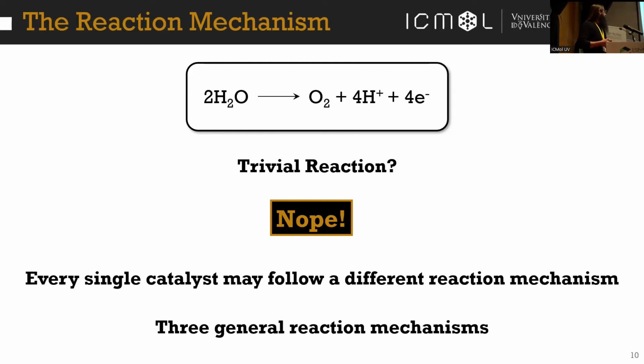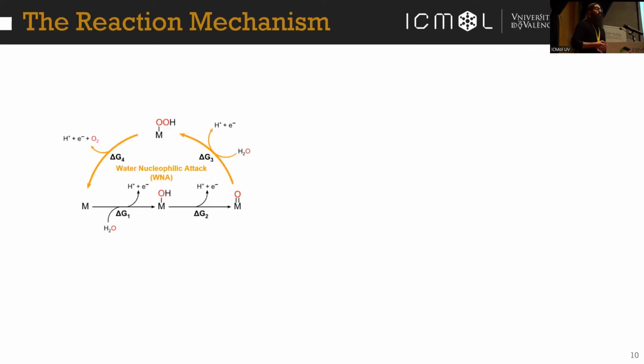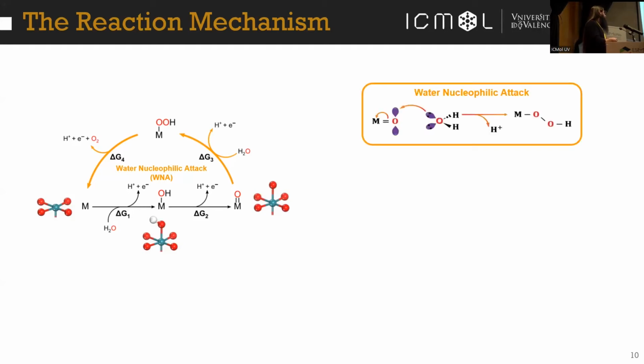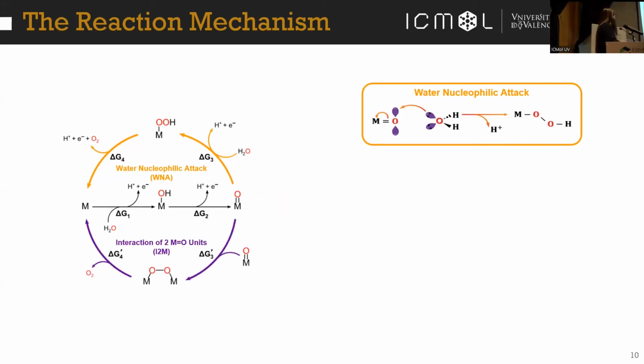So the first reaction mechanism is known as the water nucleophilic attack, in which we start with the metal of the active site, in which water binds to the metal, and after one oxidation, in which we lose a proton and electron, we obtain the hydroxyl species. After a second oxidation, we have the oxo species, and this is known as the active species because the water will nucleophilically attack this oxygen to form the oxygen-oxygen bond. Then we end up with a hydroperoxide species, and after another oxidation, we evolve oxygen and we recover the catalyst.